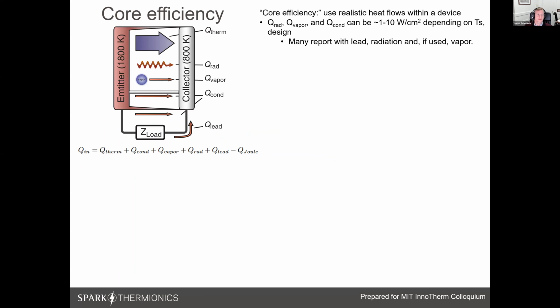And I'll just briefly explain why we think it's so important to consider a core efficiency, which is that there are a number of additional thermal pathways within a practical device. Here we've picked emitter and collector materials that are typical for historical devices. This somewhat exaggerates what I'm about to say. But there's radiation. If you're using, say, a cesium plasma, there may be vapor. There is conduction between basic encapsulation, as well as any structures or spacers to separate the emitter from the collector. And all of these can be on the order, it depends on your design, of 1 to 10 watts per square centimeter, which is where this 1 watt threshold basically comes from.